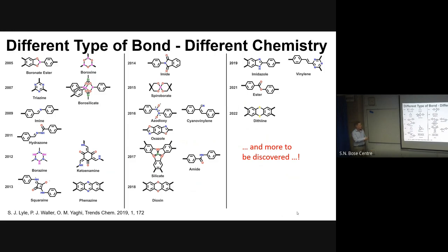And these imines were first reported in 2009. It was a very simple reaction. It's probably the most used reaction up to now. Then these ketoenamines are quite frequently used because they have a hydrogen bonding, which locks the material in and makes the material more stable. And phenazines are very interesting because they continue the conjugation inside the material.